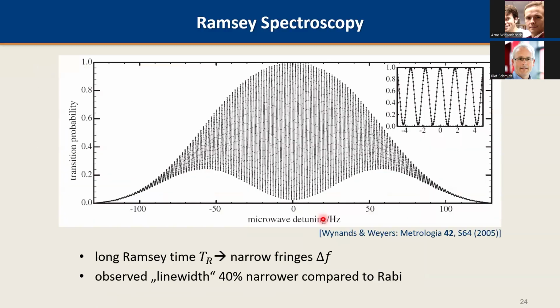And a spectrum from a cesium fountain actually looks like this. It looks very similar for atomic systems as well, but this features a very high signal-to-noise ratio, so it looks very beautiful. And if you zoom in right into the center, you can see the central fringe, which also looks, I mean, it's not a Rabi excitation because it's a sinusoidal signal here, but it provides you a center frequency and then a slope where you can measure any deviation from your phase evolution by a change in excitation probability that you get on the slope in the end.